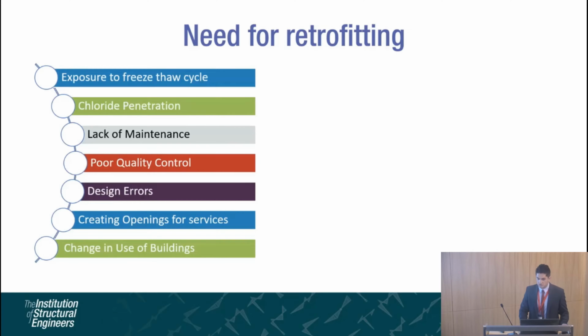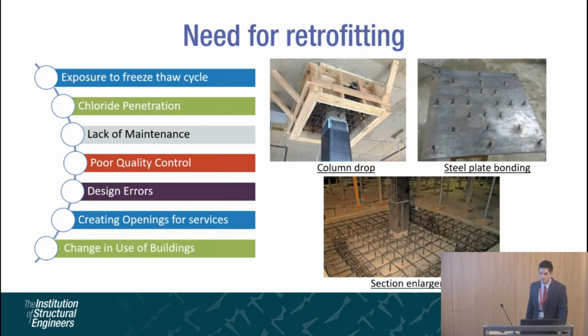The strengthening is often needed due to corrosion of reinforcement, probably due to freezing and thawing attack, chloride-induced penetration, or fire damage, or there could be a whole lot of other reasons which will require strengthening. The strengthening is often needed to increase or to restore the initial design capacity. The existing methods for improving the load-carrying capacity of flat slabs are steel plate bonding, provision of column drop, and section enlargement. However, these methods are elaborate, expensive, and are intrusive to the structures.